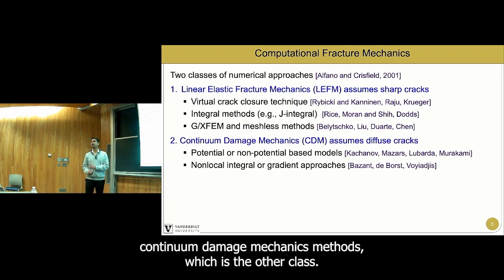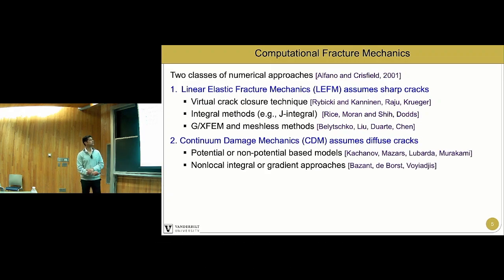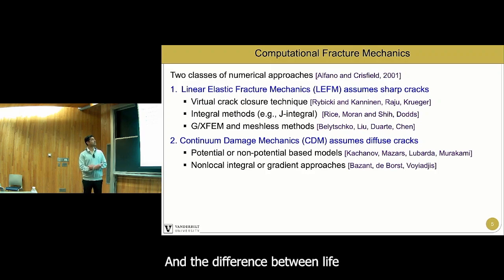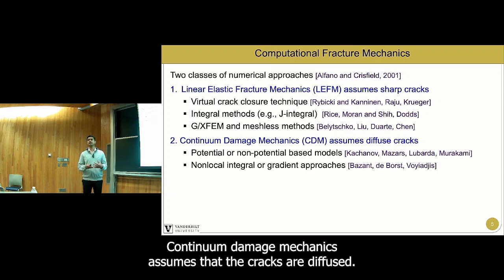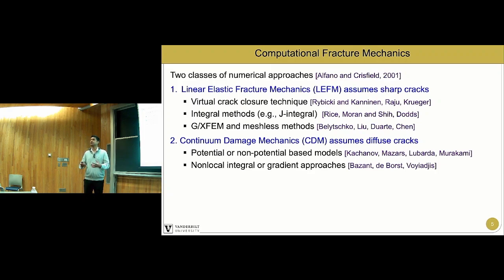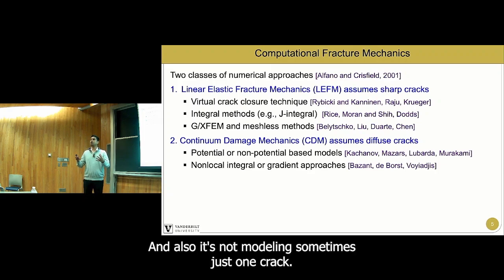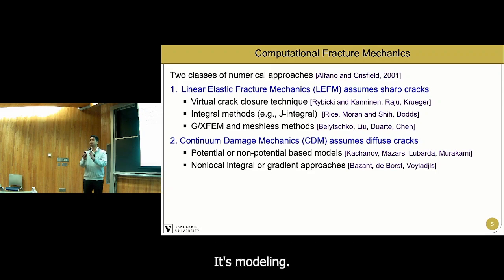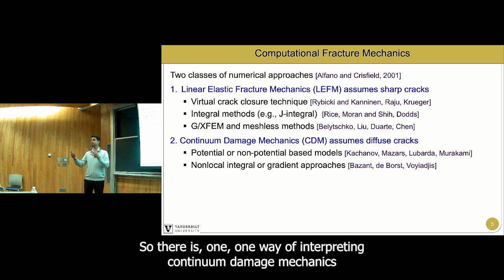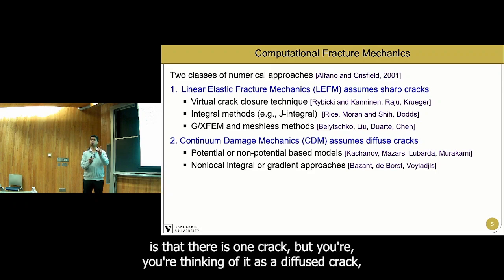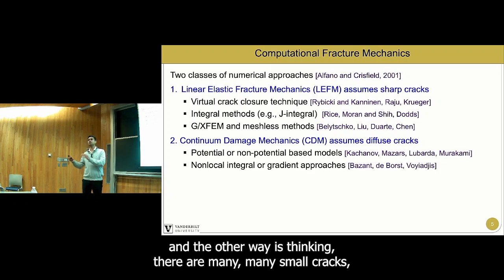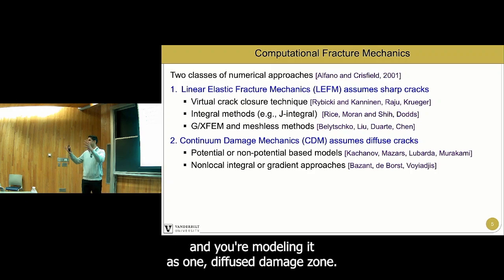Then there are continuum damage mechanics methods, which is the other class. The difference from LEFM is that LEFM assumes cracks are sharp, while continuum damage mechanics assumes that the cracks are diffused. And sometimes it's not modeling just one crack, it's modeling a collection of cracks. One way of interpreting continuum damage mechanics is that there is one crack, but you're thinking of it as a diffused crack. The other way is thinking there are many, many small cracks, and you're modeling it as one